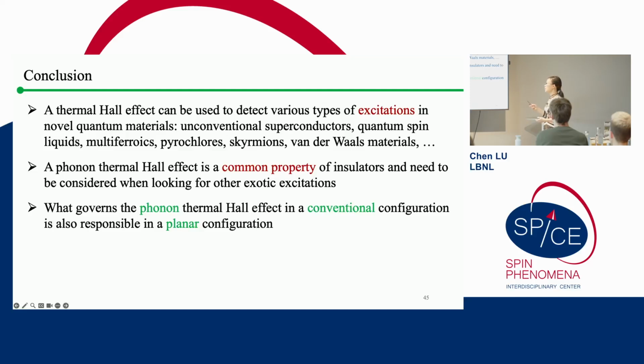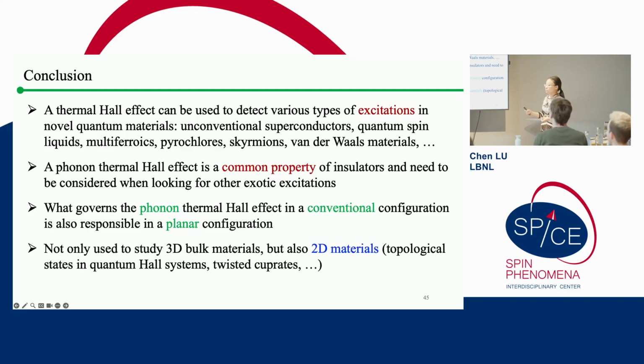We don't know. Okay. And the other message is that our study is the first observation of the planar thermal Hall effect coming from phonons, which reveals another facet of the phonon thermal Hall effect: it can show up in both a conventional and a planar configuration. This probably tells you that whatever mechanism is responsible for the conventional thermal Hall effect should also be responsible for the planar configuration.